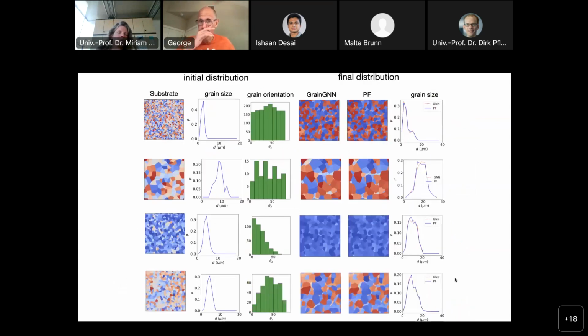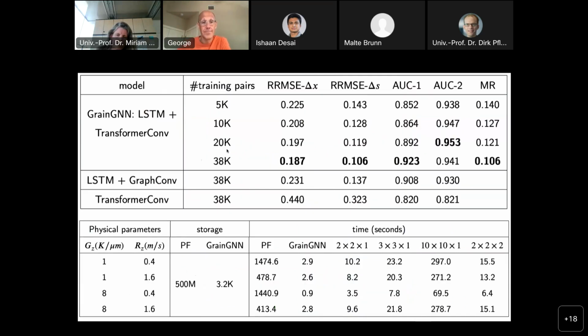And these are more examples in which we also vary the grain orientation, in which we show the effects and the variability of the quantities of interest. Here we show a little bit, in the first table, the effect of the architecture. So this is a transformer convolutional network without memory. This is an LSTM with graph convolutional, no transformer, and this is the graph LSTM transformer convolutional network, and we show the results. And this is the training size. Essentially, we use pairs of graphs at t-1 and t, and this is our training set. So we have 5,000 pairs, 10,000, 20,000, and 38,000 pairs.